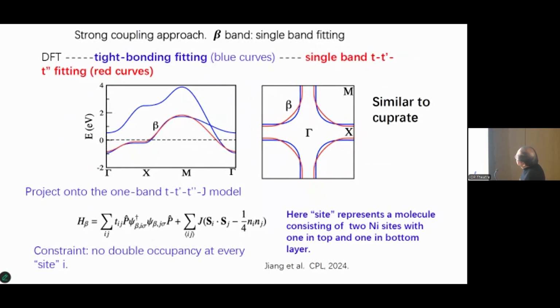So we may just try to fit this beta band by a tight binding model. We can consider this t prime, t double prime fitting. This is not so good, but it's not too bad. Then we end up with the so-called t-J model. t means this beta band hopping, and J means the spin-spin interaction of this beta band. Remember that here, the site is just a molecule consisting of two nickel sites, with one on the top and one on the bottom layer. So that model shows the d-wave superconductivity from the beta band. The alpha band is basically a free electron, not much correlation, and does not generate superconductivity much.